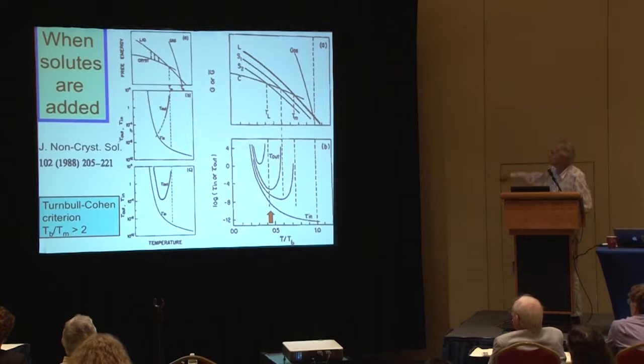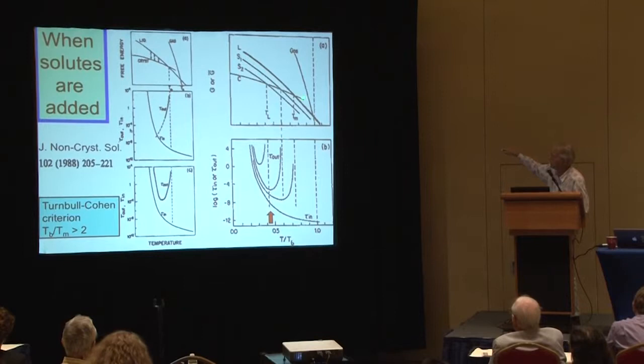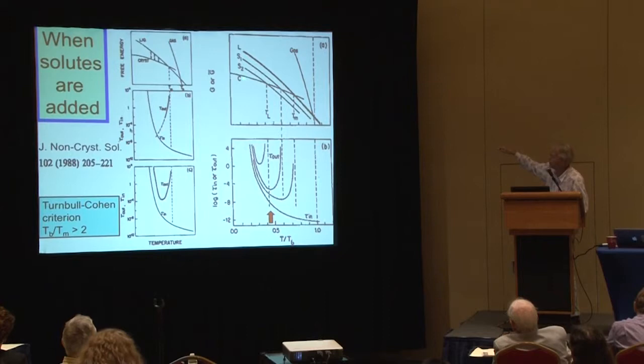In our interest today, rather than changing the liquid, we want to keep water there, so we want to change the composition of the aqueous solution. So we add different amounts of solutes, and in this way, we depress the free energy to lower and lower values relative to the crystal. The intersection with the crystal free energy curve tells you where the liquidus temperature is, and here it is happening as we add increasing amounts of solute. Again, we're pushing the nose of the TTT curve out to longer and longer values, and we end up getting a glass former, which is what we want, because then we preserve the oocyte or whatever we've put into it as an extra component.